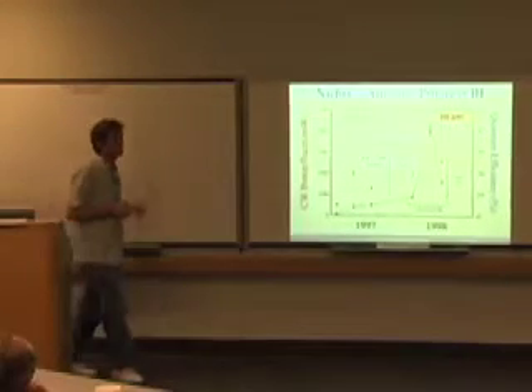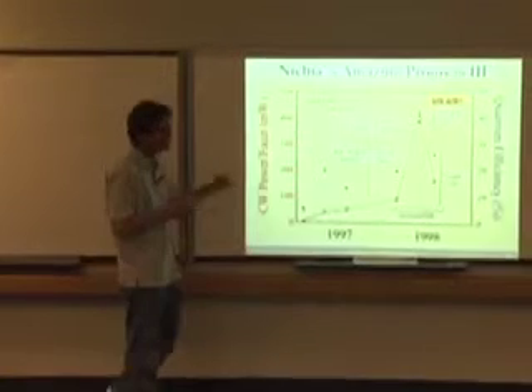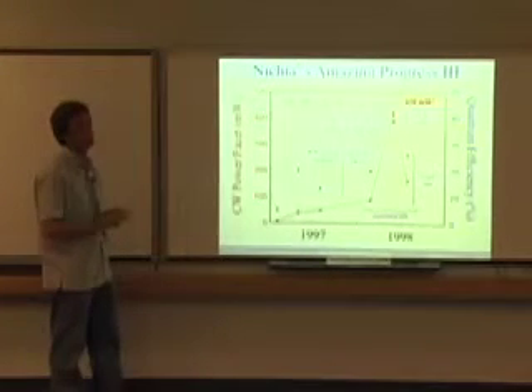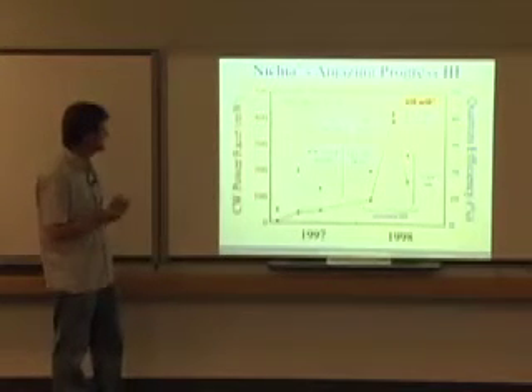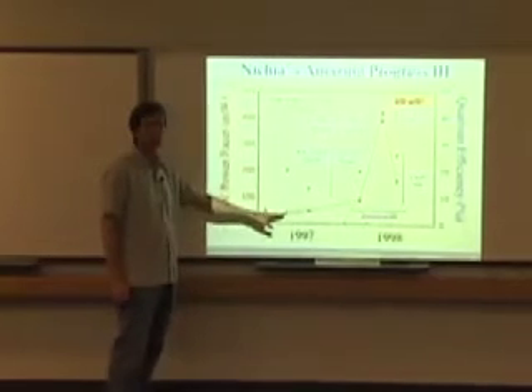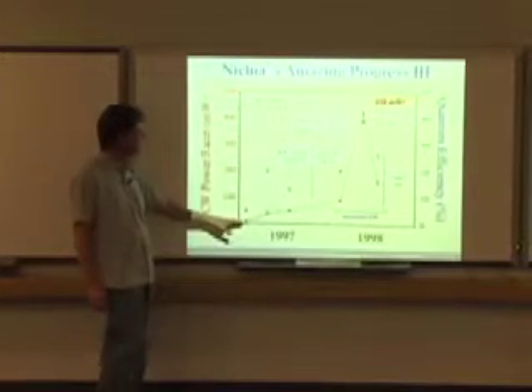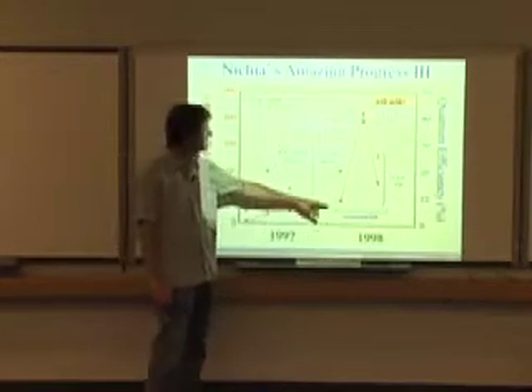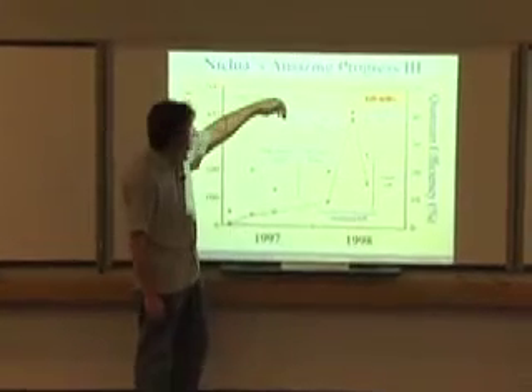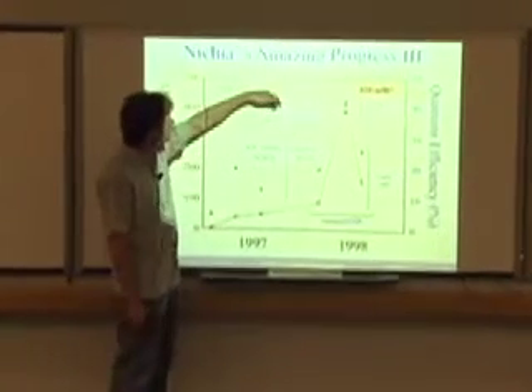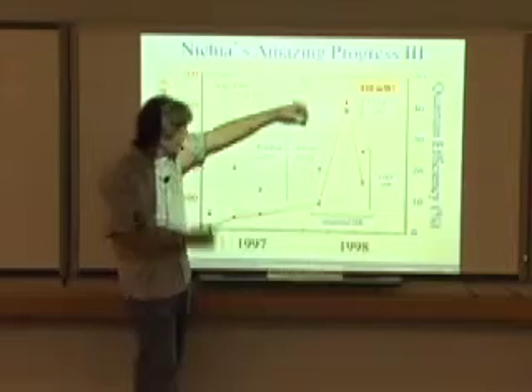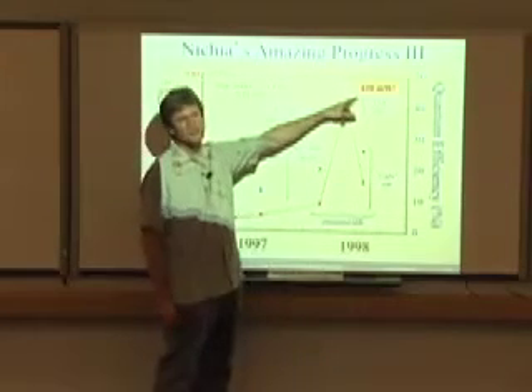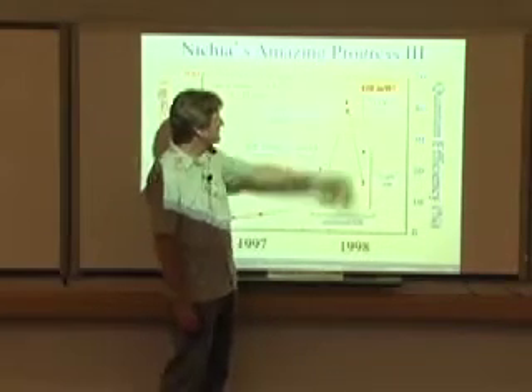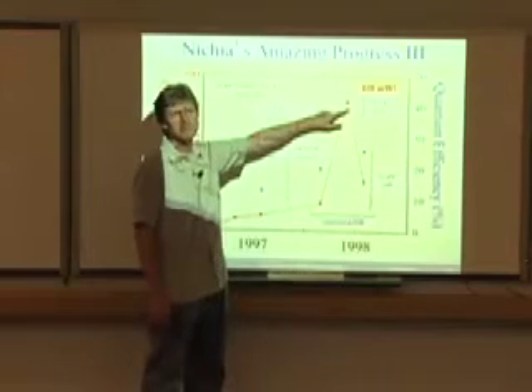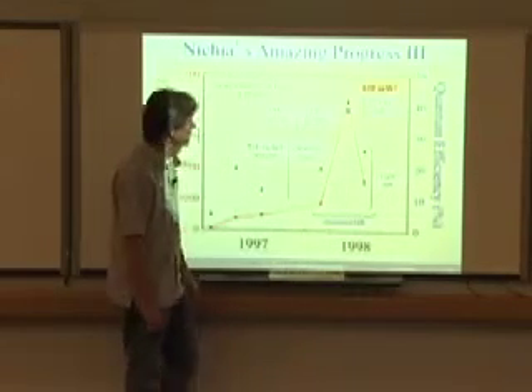So Nichia's amazing progress just keeps going. The CW output power and quantum efficiency metrics: the power started pretty modest, a milliwatt or 2 in '97, then up to 50 milliwatts. And then eventually, as they made a transition from atmospheric pressure growth to low pressure growth, they ended up getting up to 420 milliwatts of CW output power. Quantum efficiency of this one was up close to 40%, which is pretty remarkable.